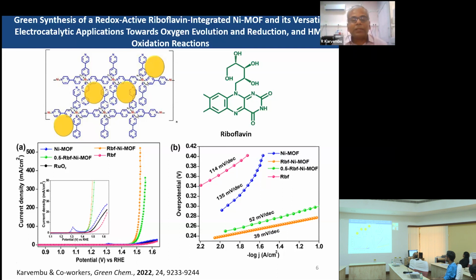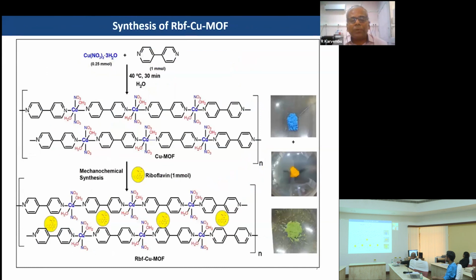Motivated by the results we obtained from this post-synthetically modified MOF, we prepared a copper-based metal organic framework. Copper is well known as an electrocatalyst for carbon dioxide reduction reactions, and copper in different forms gives different products from the reduction of carbon dioxide. That is very interesting. So using 4,4-bipyridine, we prepared a metal organic framework under very ambient conditions, at ambient temperature, in aqueous medium.